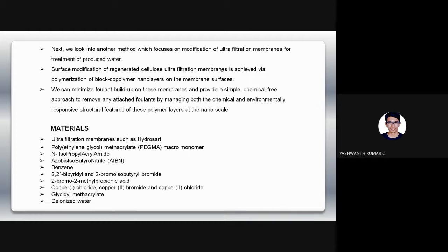The chains hydrate below this temperature to create a random coil shape but collapse above the temperature to produce a smaller structure. This is commonly used to build temperature responsive materials, including several instances with membranes, because its physical and chemical properties can be easily controlled by changing the temperature. As a result, membrane surfaces were grafted with this to make them temperature responsive.